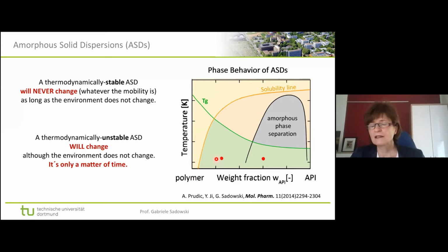And this is the second effect the pharmacists take advantage of. So it's not only that they want to solubilize the API in the polymer, but mainly they hope that by Tg, they can at least kinetically stabilize what they have. But of course, it's also interesting to know what the supersaturation is, what the driving force to crystallization or to phase separation is. And actually what we are doing in our group is to find out where these three lines are for a given polymer-API system. Usually you can change the polymer, but you cannot change the API. So the API is what the medicine should contain, and you could select the best polymer for a given API by, for example, looking at these three lines. So this is more or less what we are doing and what the talk will be about.